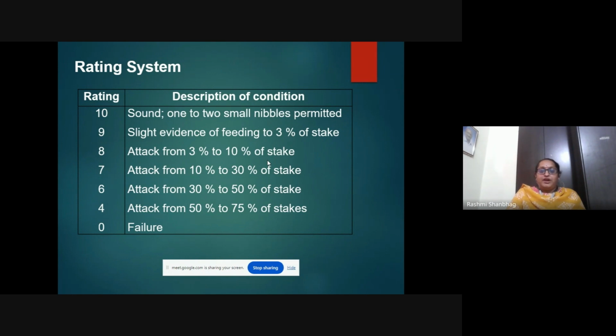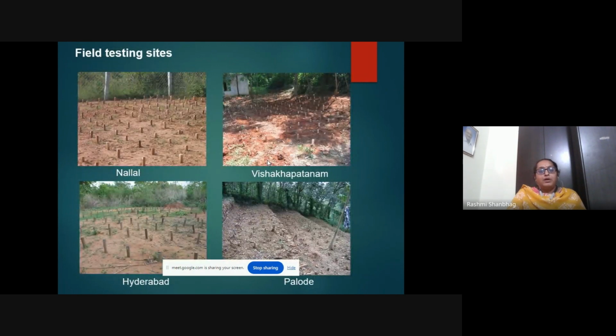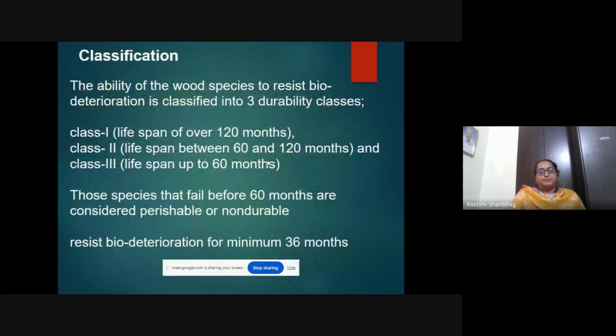If the wood is very sound and without any attack, the point assigned is 10. Whereas if more than 50% attack is there, then it is considered as a 4, and for total failure, 0 points will be given. These are our field testing sites where we actually inoculated the test samples.